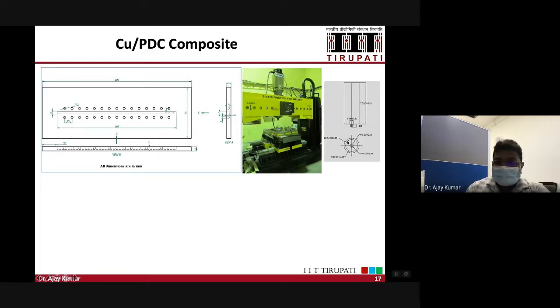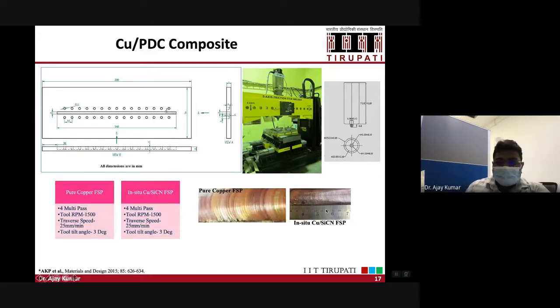And this is the design for the FSP tool. We use the 6 mm thickness of plate, and you can see here the design of the tool. Then we did the FSP on the matrix material copper as well as on the composite. We optimized the process parameters. So we did 4 multi-pass processes at 1500 RPM and 25 mm per minute tool speed, and the tool tilt angle was 3 degrees. This tool tilt angle is very important in the friction stir welding process. In the previous talk, you must have learned that this tool tilt angle provides a backing or forging force, or support. If you don't have this, then you will have a lot of cracks during the process.